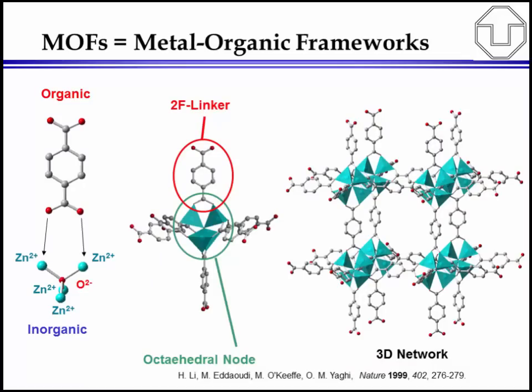Yeah, and this is possible due to the unique architecture. The unique architecture of metal organic frameworks is that it uses basically a node and linker concept. The node, you can see that on the left-hand side of the slide, is always an inorganic subunit. For example, here the well-known example from Omar Yaghi, who is one of the pioneers in this area, the zinc 4O cluster as observed in MOF5, which is connected to a very simple organic ligand, a carboxylate. Here it is a dicarboxylate, terephthalic acid.